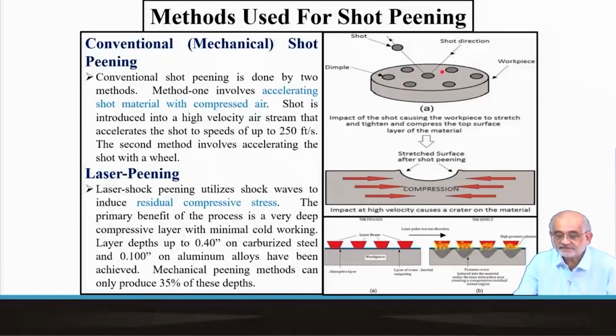Now, how do you do that? So, this is the surface. So, these are indentation marks. So, here is a single impact which is happening, and because of which the shot, after hitting this point, is reflected back. And depending on the angle and velocity and the diameter, elastic modulus, all these material and process parameters, the amount of impact that we develop here and the corresponding deformation level and its character is created.